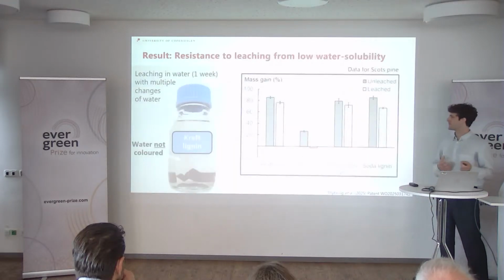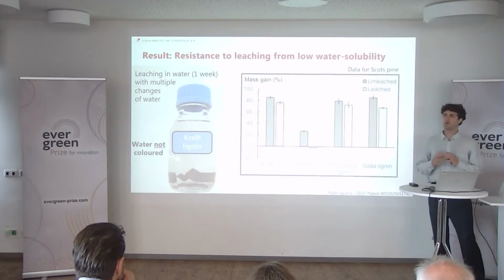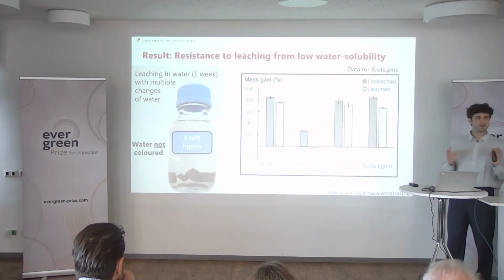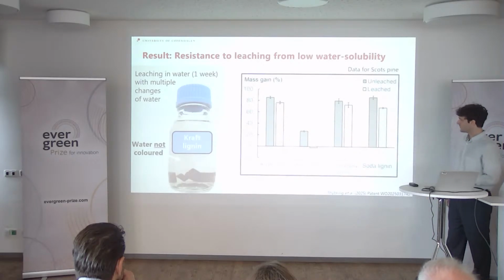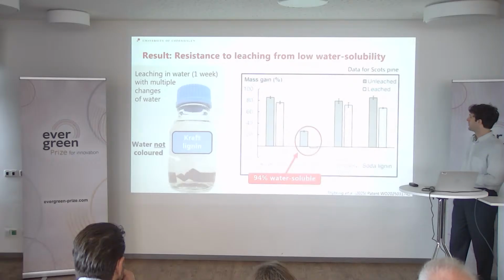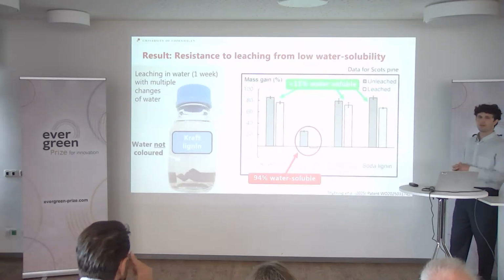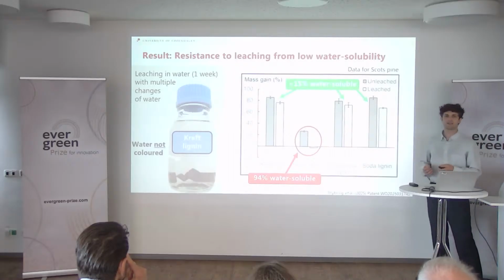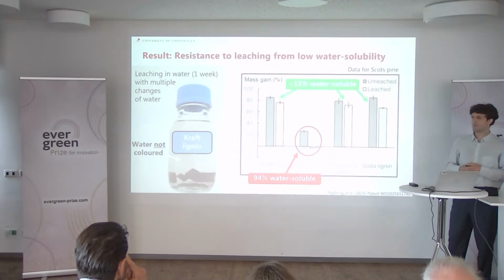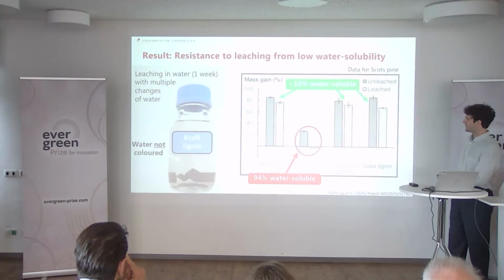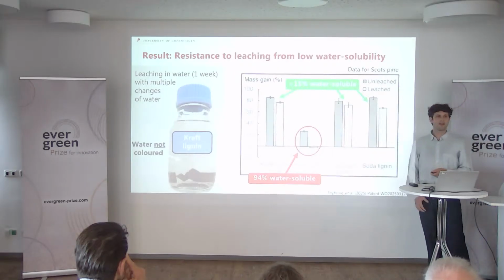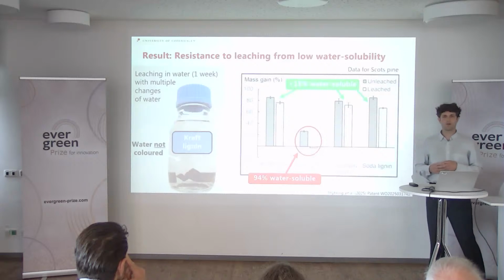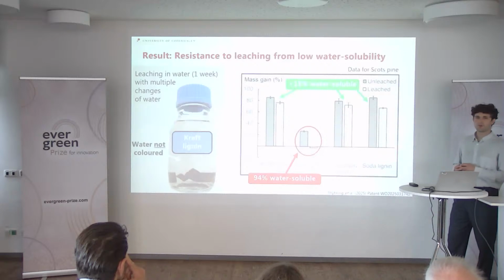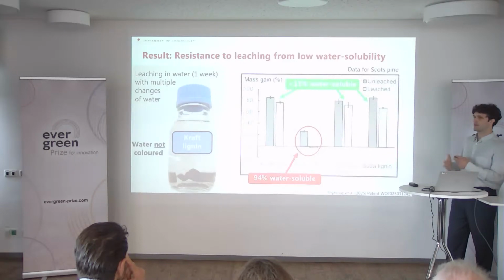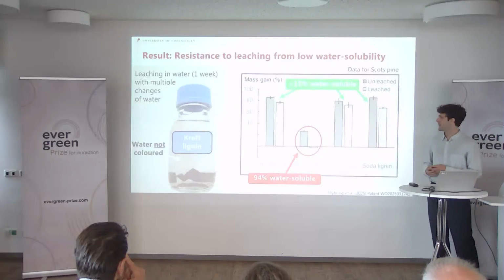But lignin is very not homogeneous out there. There are lots of types. Do they all work? So we tested several of them and we figured out that the ones that work best are the ones that are less water soluble, because the others don't stick very well to wood. Luckily, kraft lignin is one of the main streams from pulping and paper companies. So what we are actually using is the one that is most readily available in the market.